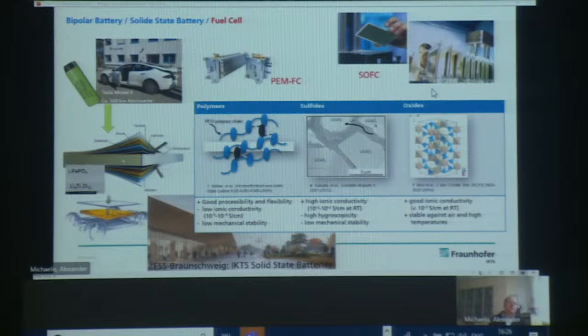Right now, we have quite good results on these technologies. So we use cobalt-free batteries for this. But this bipolar battery still contains liquid electrolyte. The next step is to substitute this liquid electrolyte with a polymer electrolyte. And then the next step is to substitute the polymer with a solid electrolyte, a sulfide or oxide-based pure ceramic system. So this is what we are working on right now. And here safety and power density would significantly increase.